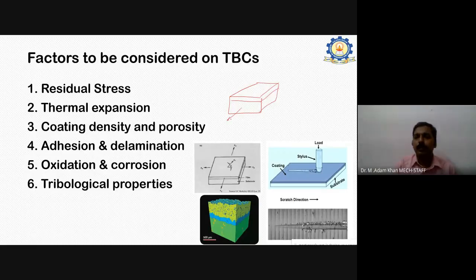If I talk about the stress of the substrate and the coating, sigma x or sigma y, what is happening? This will have a stress with reference to the x and y direction, and this will also have a stress with reference to the x and y direction. So this can be the coating, and this can be the substrate. We cannot say that the strain in this material is the same as the strain in this substrate. Coating strain and substrate strain are different.